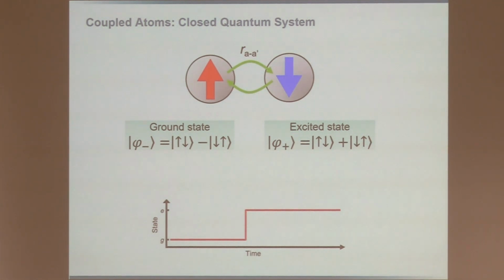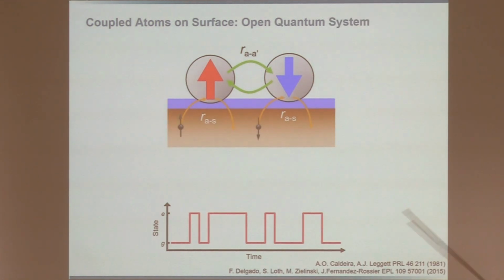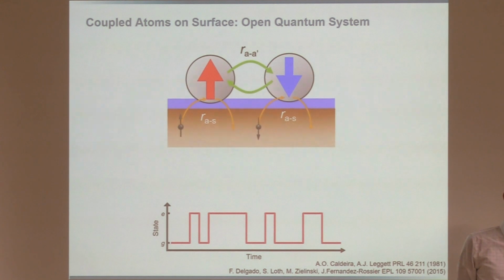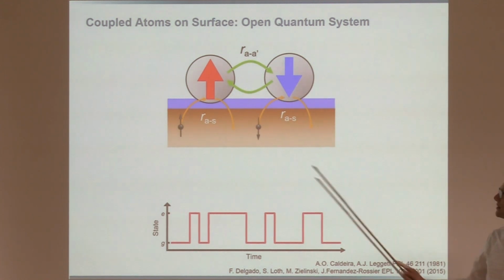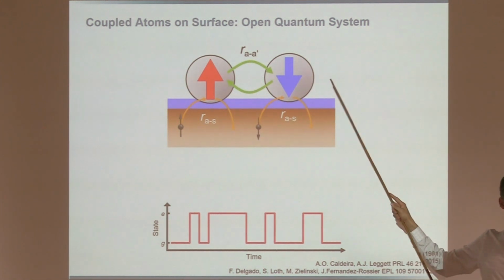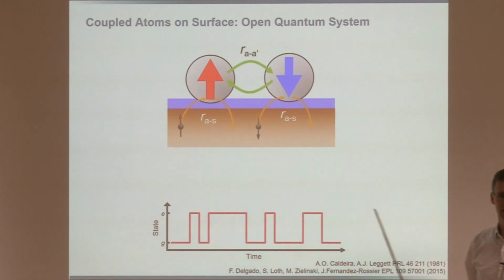The problem that we're facing, at least in scanning tunneling microscopy, and I guess also in break junction or electromigration devices, is what happens when a scattering electron comes about. To the best of our knowledge, over the past 10 years, all experiments we have conducted on molecules and structures that we have assembled can be fitted by saying that an electron out of the substrate does not scatter with the spin states of the entire object, it scatters locally on an atom. This is not proven at the moment, it is just that all our experiments fit with what we observe.